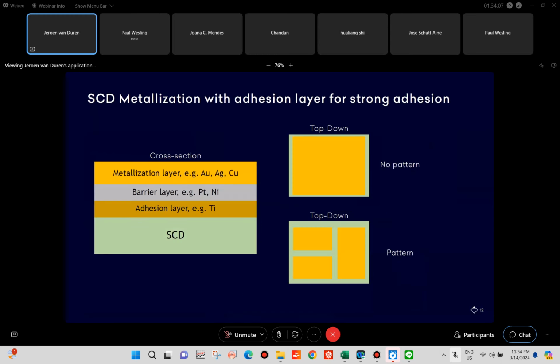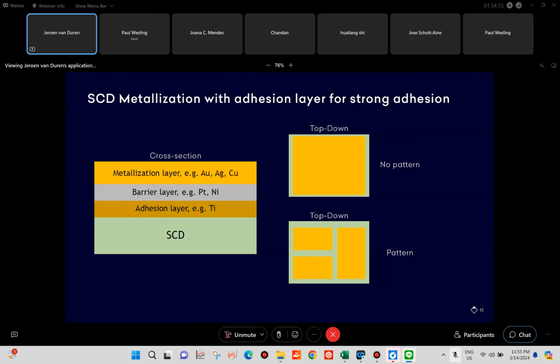Metallization. Now, as Joana mentioned, diamond is chemically really inert. So to get good adhesion, you do need an adhesion layer. A very typical adhesion layer is titanium. Barrier layers depend on what you put on top for the metallization, but typical barrier layers are like platinum and nickel. Metallizations depend on the bond technology or assembly technique that you're using, but gold, silver, and copper are offered on the diamond. And as with any metal stack, they can be patterned or they can be left uniform depending on the use. So again, the diamond is very easily integrated, and to deal with the chemical inertness, it's putting down a proper adhesion layer on the diamond.